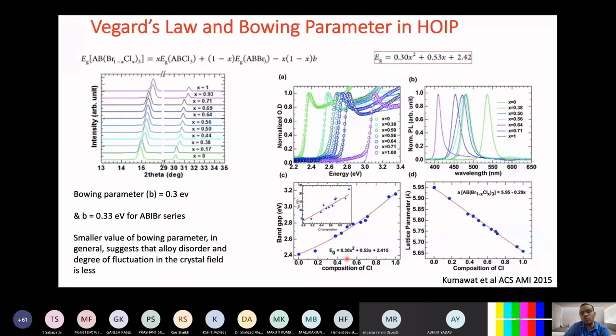That is very low as compared to what is seen in the inorganic semiconductors, the gallium indium nitride family. Because as I was telling, you can have gallium nitride, you start mixing in indium, and you can go from blue to green. The same thing, you have MAPbCl3, start adding bromine, and you can go from blue to green. And then you fit that data using Vegard's law. So you have your XRD data, which can be used to plot the lattice constant versus composition. You have your UV-vis data, which you can fit and determine the actual electronic band gap by removing the contribution from the excitonic peak. Then you can get the electronic band gap changing as a function of composition.